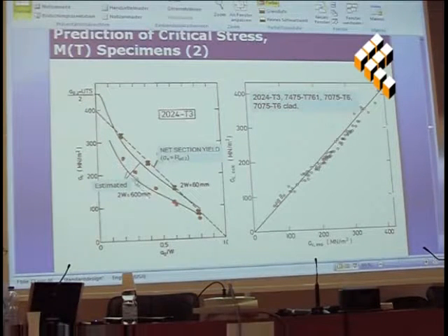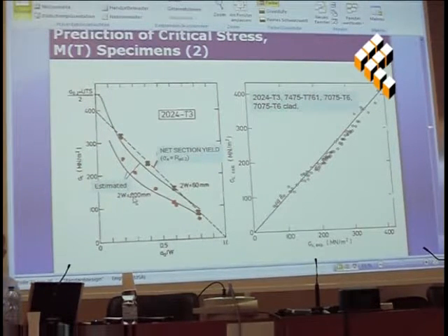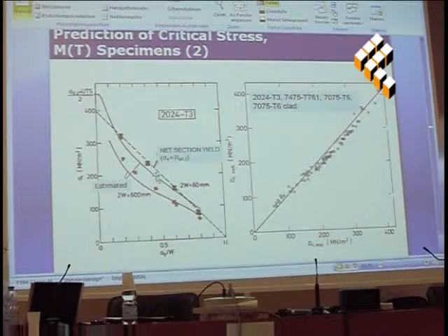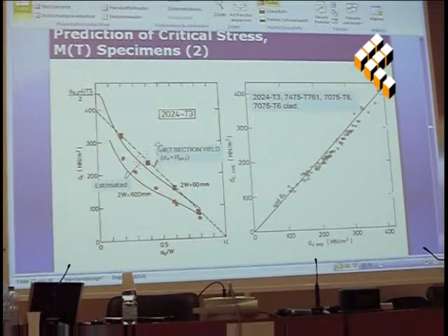This is a wide plate with 600 millimeters, and the structural component may be even wider here. And you see there is really a size effect with respect to toughness behavior, ductility behavior of a test piece or structural component. It can be made ductile, it can be made brittle. It is brittle down here, it's ductile, and it gets up here.